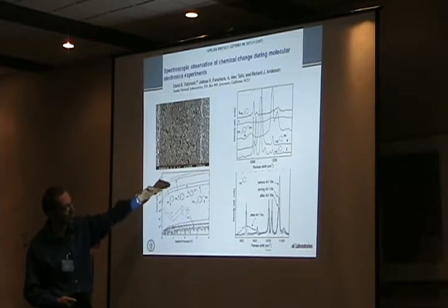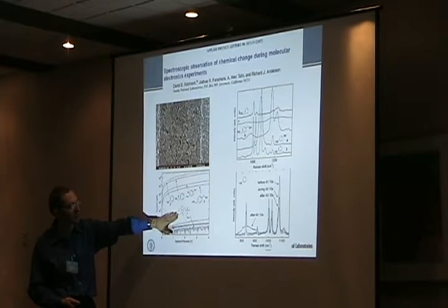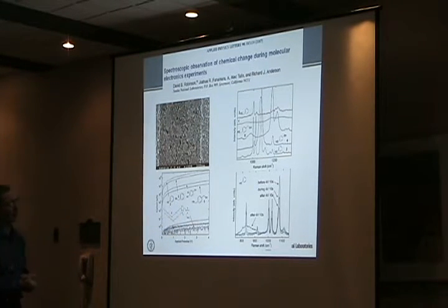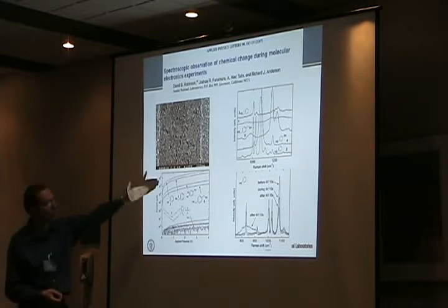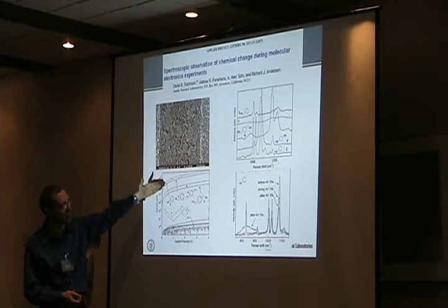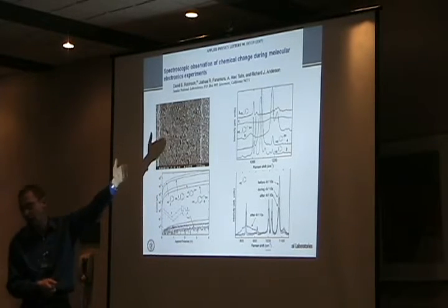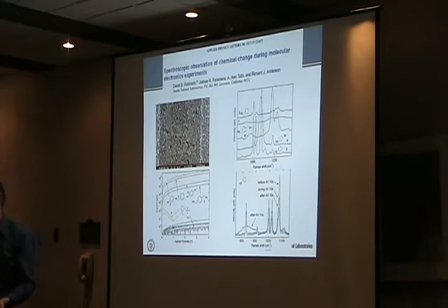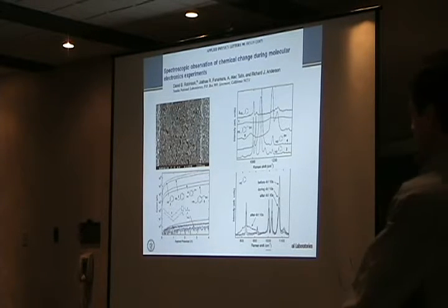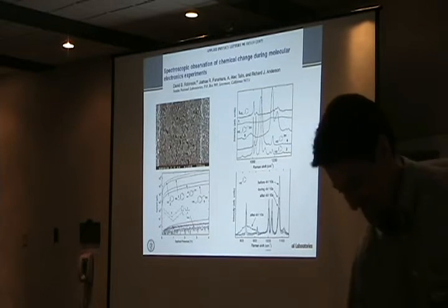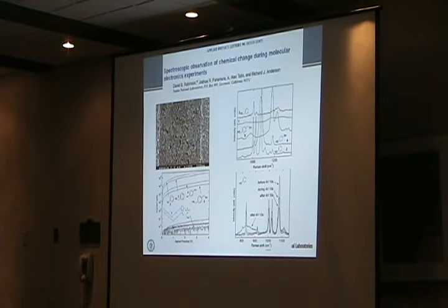When we substitute the initial molecule, in this case an amine, with thiobenzene, for example, we see a huge change, a drop in the resistance. It's very, very reproducible. And we can now tell with Raman that indeed the molecule is there. And we can also see changes when we apply high bias, the Raman changes and the electrical response.